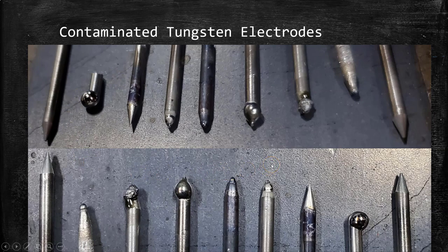for use. So we can take a look at any of them and see that their shape has changed, whether it's because we've used the wrong polarity, whether we've made contact with the base metal with our tungsten, whether we've made contact between our tungsten electrode and the filler rod, whether we're using a too low flow of shielding gas, so not enough shielding gas, whether we're welding with no shielding gas, maybe our amperage is set too high, so you see some discoloration with these tungsten electrodes, so you know that they've been overheated. You've probably got some microfractures in there, which leads to tungsten spitting. That's not good. So a lot of different things that lead to contamination.